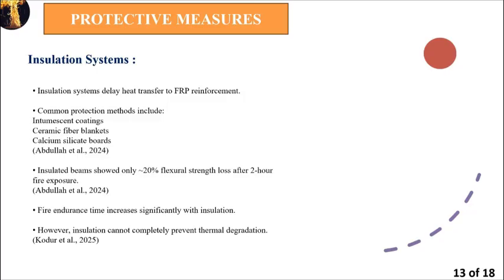In some cases, beams protected with insulation experience only about 20% loss in flexural strength after 2 hours of fire. So this is a significant improvement compared to unprotected members. However, it is also important to understand that insulation systems delay the temperature rise, like the concrete cover, but they do not completely eliminate thermal damage. If the fire lasts long enough, degradation of the FRP will still occur.